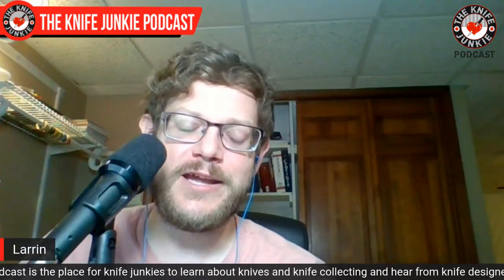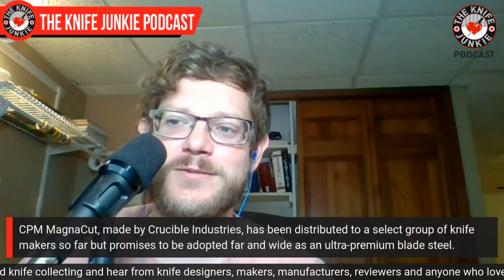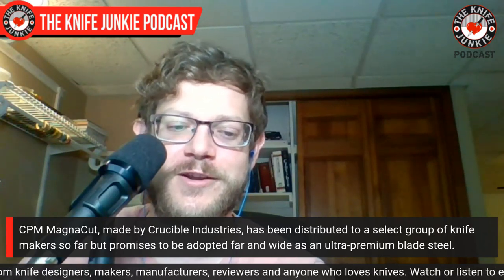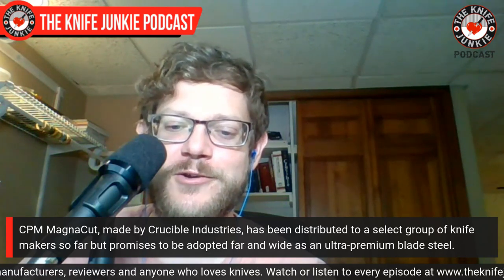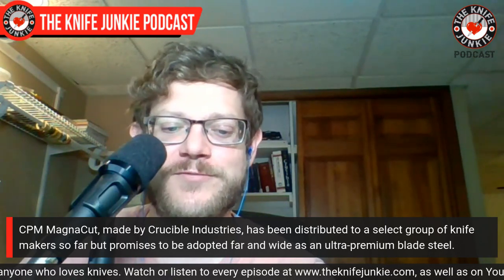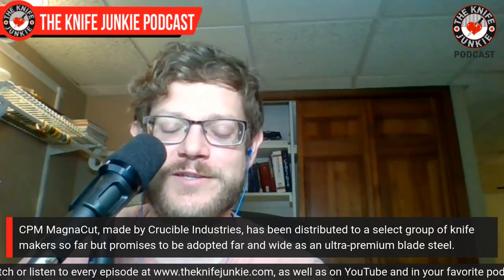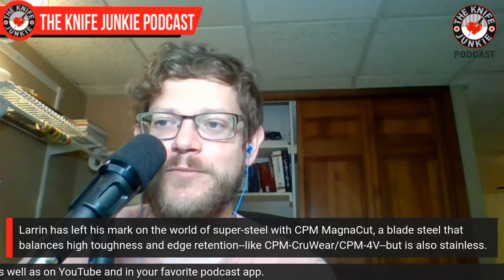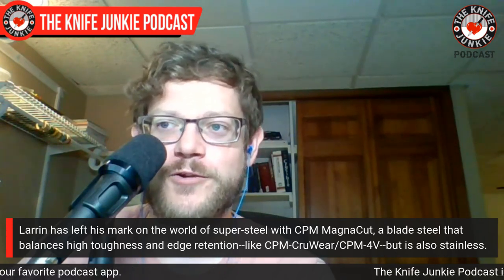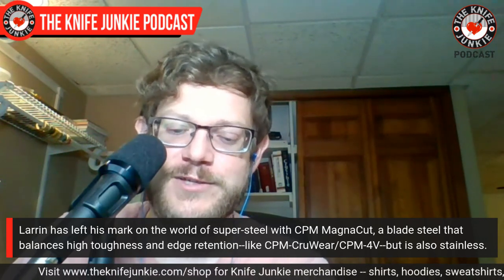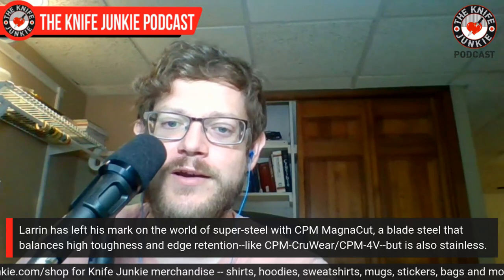But, you know, sometimes good ideas are not used for a reason, and that's because initially they don't look correct. So I put together this presentation. I had all my experimental work, because it's not just that you tell the modeling software, hey, I want a steel that has this much edge retention and this much toughness and this much hardness, and it spits out a composition for you. It can tell you predicted breakdown of phase fractions. So you have this much austenite, this much of this carbide, this much of this carbide at this temperature, and then those phases have this composition. It'll tell you you have 0.4 carbon in solution and 11.1 chromium in solution, but you don't know what hardness and corrosion resistance that's going to give you unless you've got a bunch of experimental work on different steels.